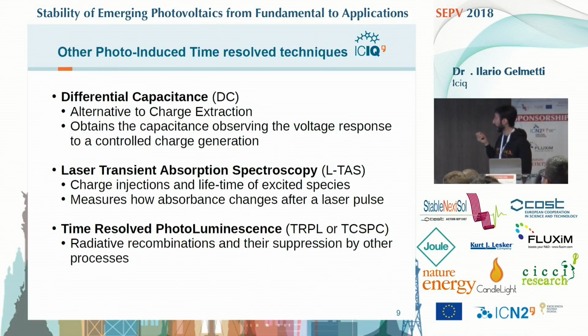Anyway, other techniques that we usually use but will not be used in this presentation are differential capacitance, which can basically give similar results to charge extraction. With this technique we can obtain the capacitance by observing how the voltage changes when adding a small extra charge with a laser pulse. And laser transient absorption spectroscopy is quite popular, and it can observe, over a wide range of time scales, charge injections and lifetimes of many of the excited species present in the whole structure, basically by observing how the absorption changes after a laser pulse.